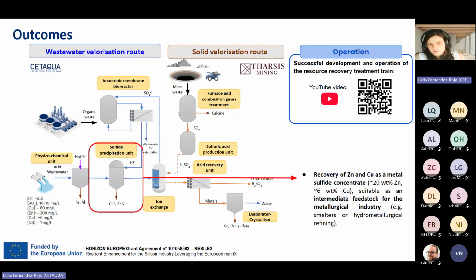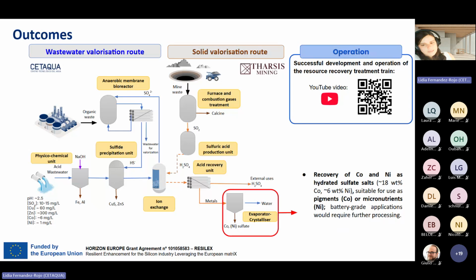Then, as I said, with the biogenic sulfide produced, we were able to recover zinc and copper as a metal sulfide concentrate with 20% zinc and 6% copper. And these were suitable as an intermediate feedstock for the metallurgical industry. And then in the last step of the treatment train, we were also able to recover cobalt and nickel as hydrated sulfate salts with 18% cobalt and 6% nickel. And with this quality, these were able to be used as pigments in the case of cobalt or micronutrients in the case of nickel, as well as feedstock concentrates also for the metallurgical industry. However, battery-grade applications will require further processing.